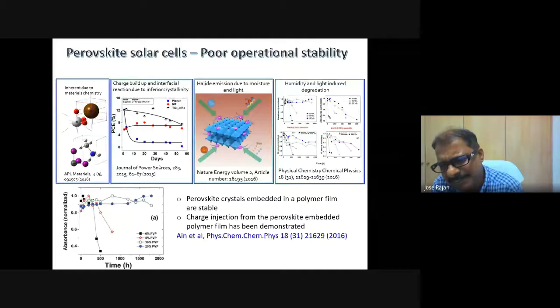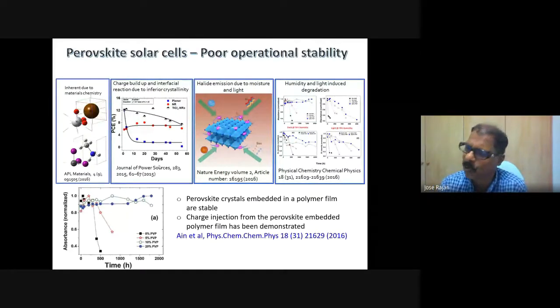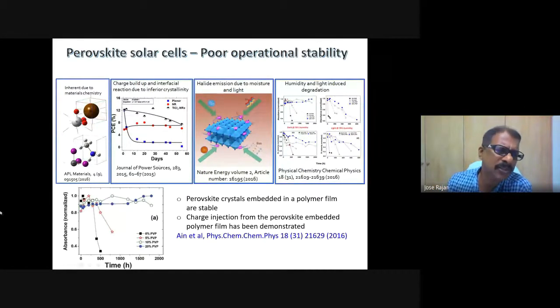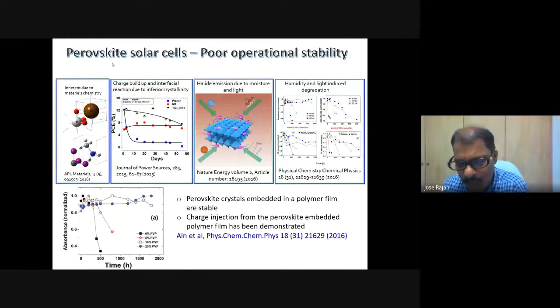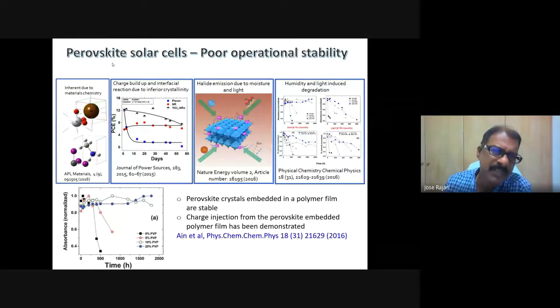And when you look into the geometry of this perovskite crystal, you would see that the octahedra in methyl ammonium halide perovskite are tilted. That means there is an electric field due to the octahedral twist in perovskite, and you have a polar entity at the middle of the perovskite lattice, at the A site. So there are two competing electric fields. When there are two competing forces, how can it be stable? So there is an intrinsic instability because of the mobility associated with the methyl ammonium ion.